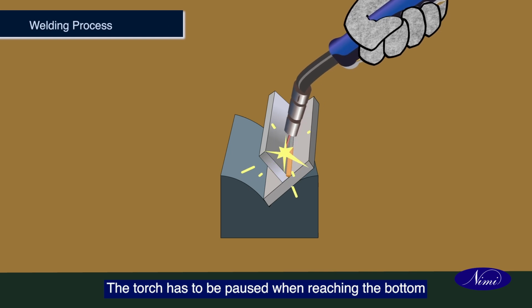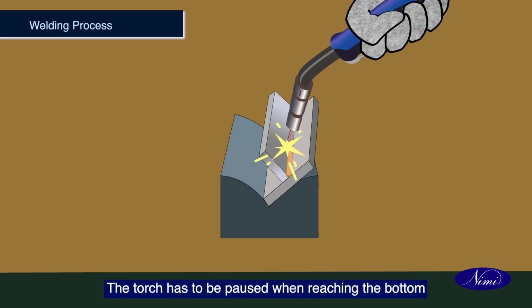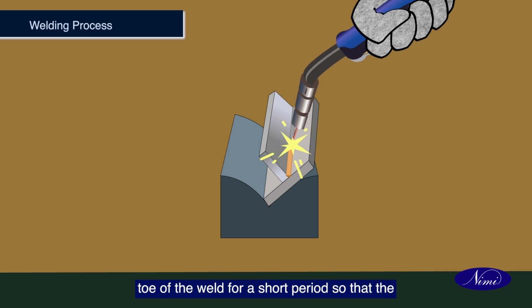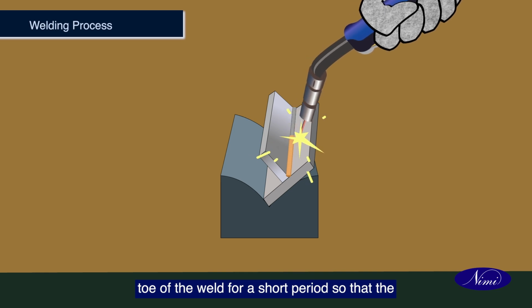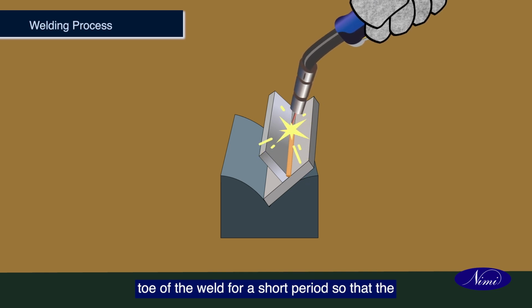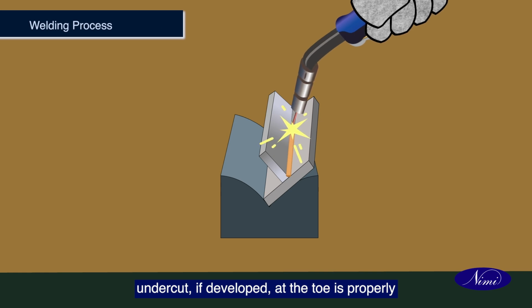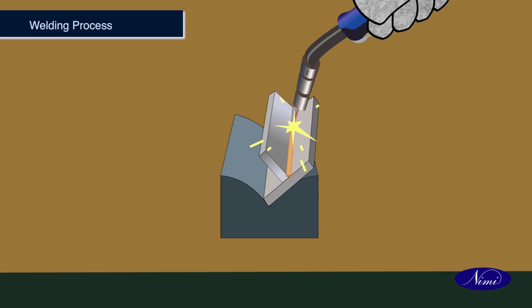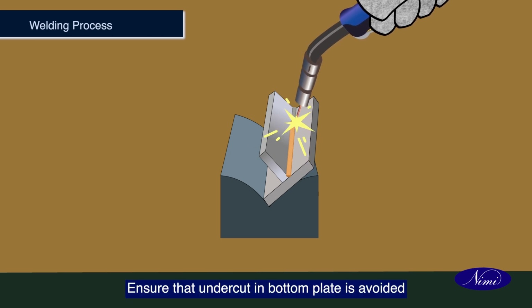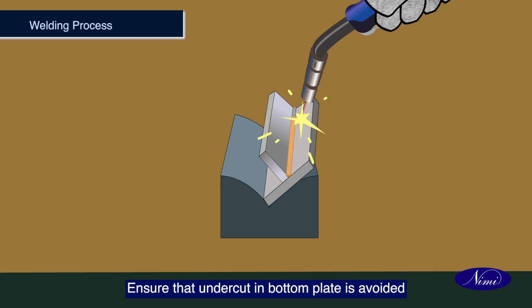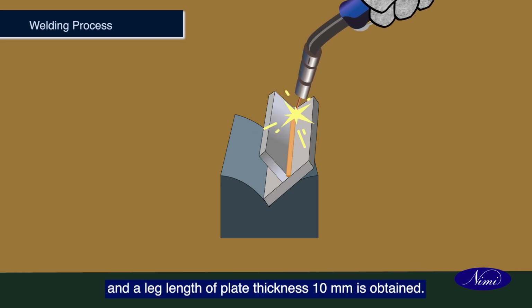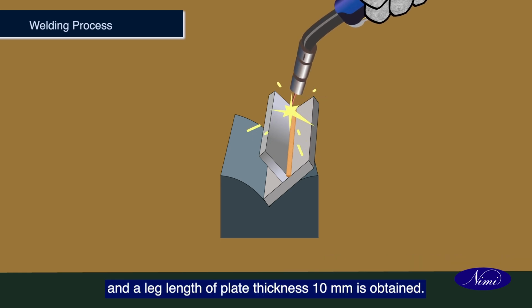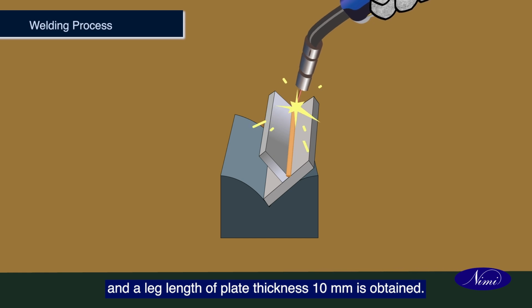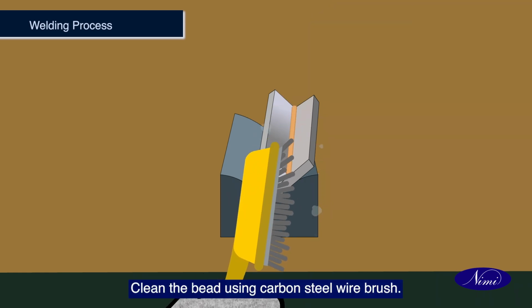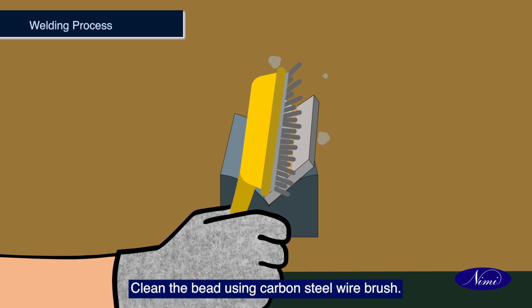The torch has to be paused when reaching the bottom toe of the weld for a short period so that the undercut, if developed, at the toe is properly filled with filler metal. Ensure that undercut in bottom plate is avoided and a leg length of plate thickness 10 mm is obtained. Clean the bead using carbon steel wire brush.